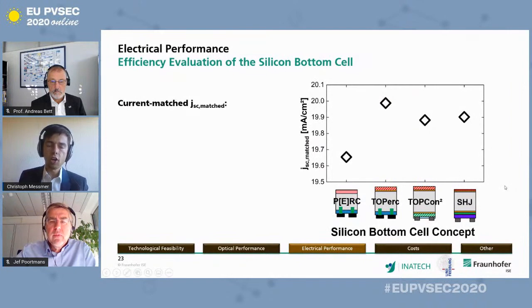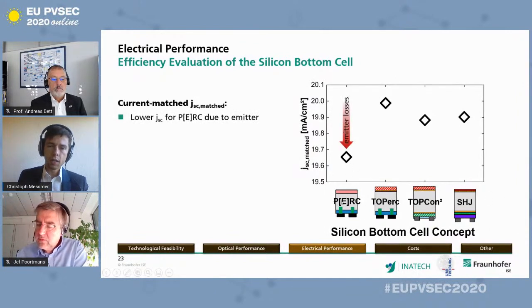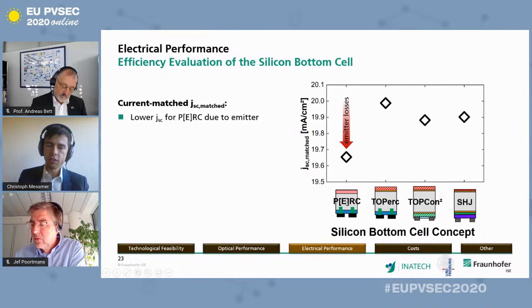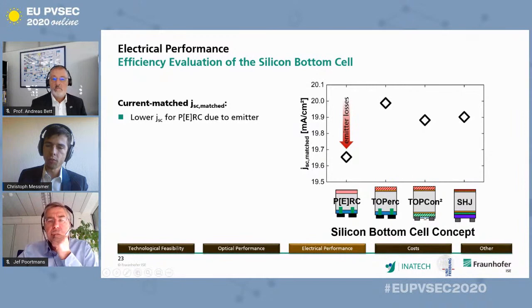Here you can see the current matched JSC for each bottom cell concept I presented before. And first of all, you can see that the PERC-like bottom cell has the lowest JSC, mainly due to emitter losses of the unpassivated emitter. The other cell concepts gain higher JSC, and the JSC here is mainly counterbalanced by the parasitic absorption in the TOPCon layers and the TCO layers.